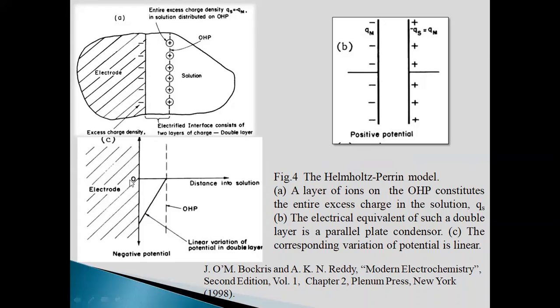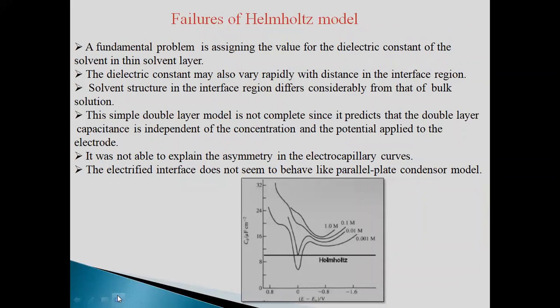And this boundary has a distance xh, and this can be drawn in analogy with the two parallel plates of a capacitor. Now, the reasons for the failure of the Helmholtz model. The main reason for the failure of this model is assigning the value of the dielectric constant of the solvent, which changes with the distance in the interface region. The model is not complete as it predicts that the capacitance is independent of concentration and potential applied to the electrode. Moreover, it was not able to explain the curve for the differential capacitance with the potential.